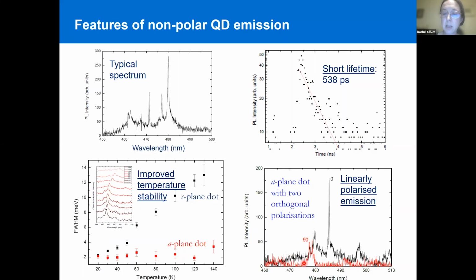We've got the emission here at two orthogonal directions in terms of the polarization. You can see that for this emission here, at about 485 nanometers, we've got nothing at all in the 90-degree orientation and a very, very strong emission in the 0-degree orientation.